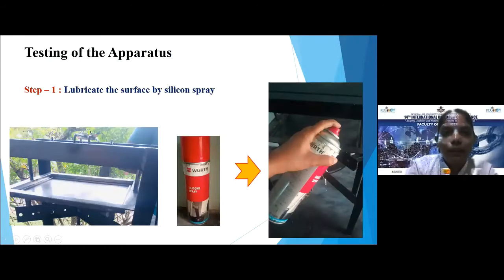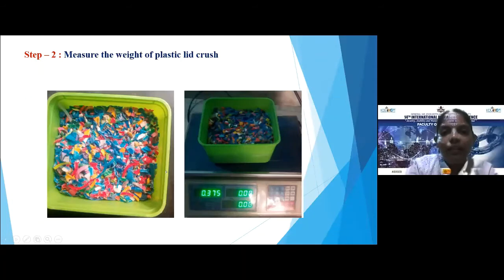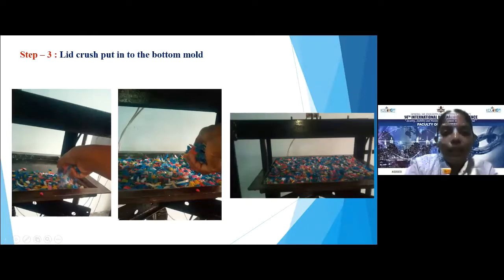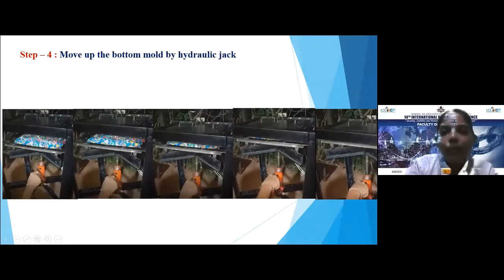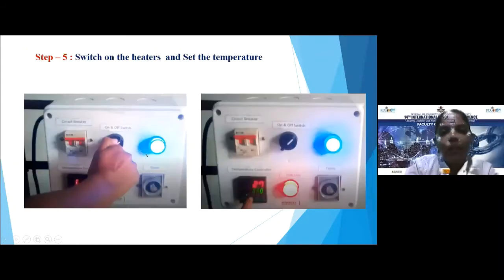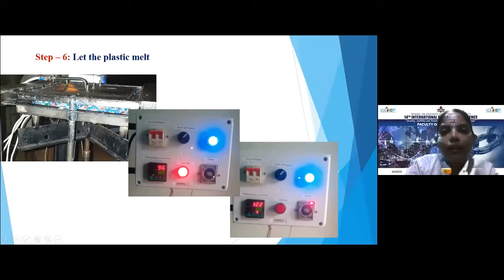Testing of the apparatus. The first step is to lubricate the surface of the mold. For that, I use silicone spray. Measure the weight of the lid crush, then put the lid crush into the mold. Then move up the bottom mold using the hydraulic jack. Then turn the heaters on and set the temperature. Then let the plastic melt. After 10 minutes, the heaters automatically turn off.